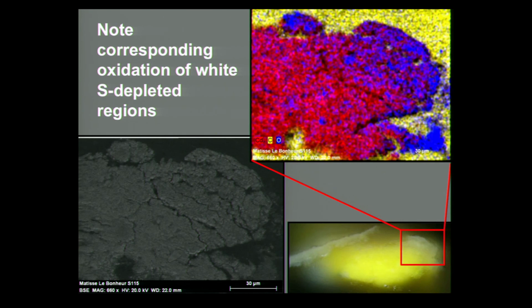And we can even see, if we map the oxygen content of this region of the paint layer, that we have quite literally an oxidation. Oxygen is shown in blue here. And so oxygen is essentially replacing sulfur in this region of the paint layer where it's fading to white.